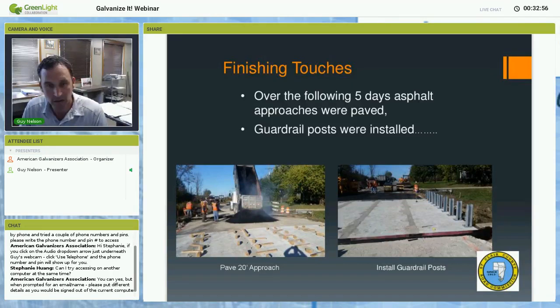Once the joints were cast, the next thing to do is put down guardrail posts, and you can see on the left they're applying asphalt to the approaches. Again, we wanted to minimize the amount of road work that needed to be done. We only needed to go out 20 feet. We matched the existing structure depth.